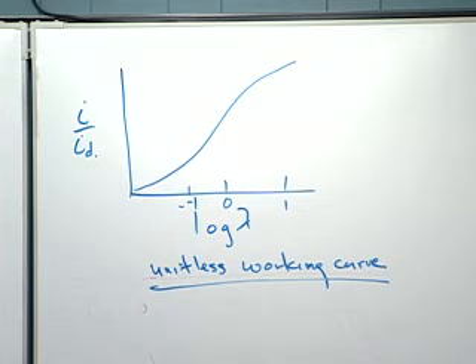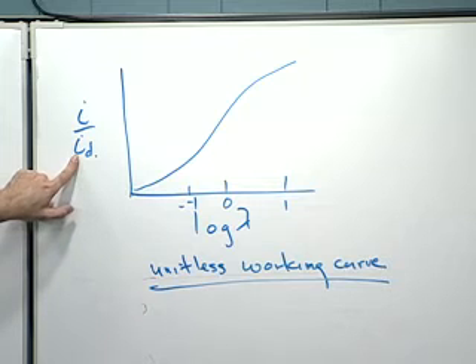Okay. So in other words, I would do this at a series of different times. I'd get a plot here, and I'd extract presumably the rate constant given the diffusion coefficient. How would I get the diffusion coefficient? I do a very large potential jump, which takes us to the pure Cottrell solution, and calculate the diffusion coefficient from that data. Okay, so I need that large potential jump because I need this current anyway for all time.